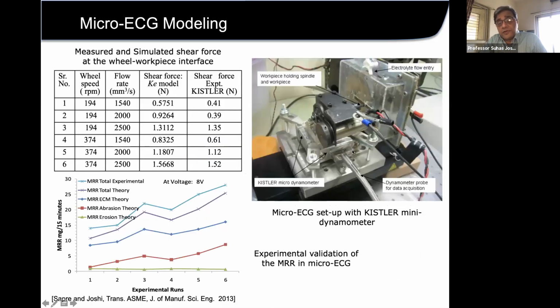Another thing we did was that at that time those very small mini dynamometers came into the market. They were very costly, but we were fortunate to be able to buy them through some of the funding, and we tried to measure the forces coming onto the workpiece during the grinding process, and tried to calculate the shearing forces through the measured shear stresses applied in this region, and the downward forces measured using the dynamometers. We got reasonable agreement, but it's not that accurate. But definitely we could get in the same range, at least the forces and the shearing stresses are in a similar range.